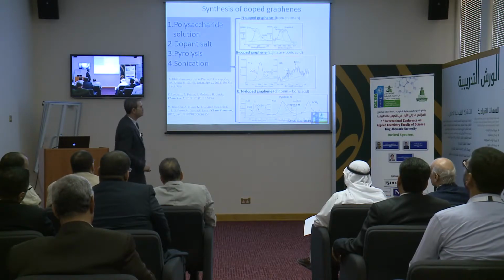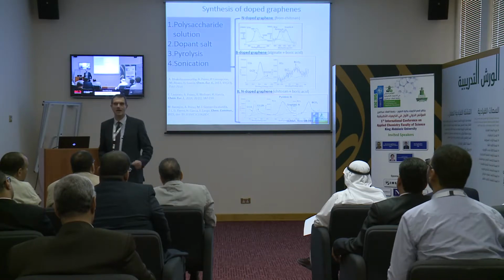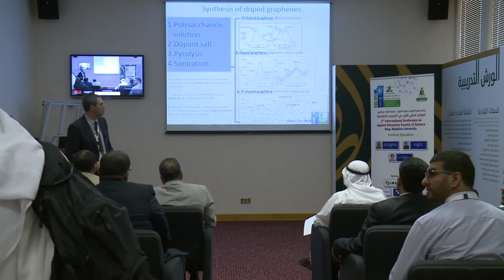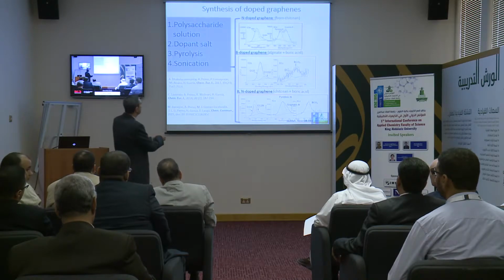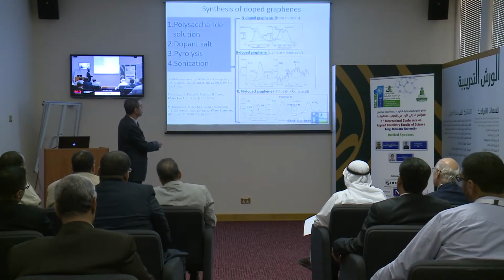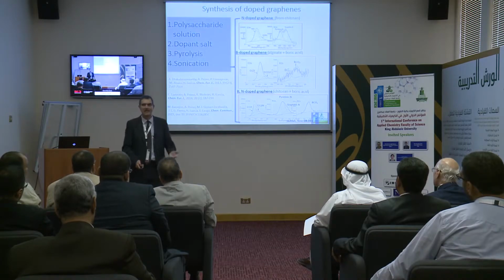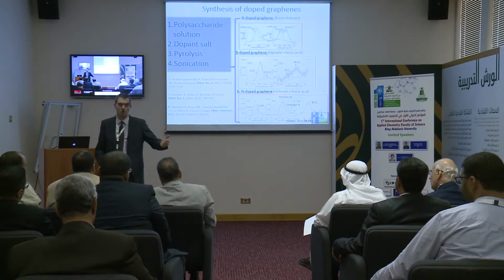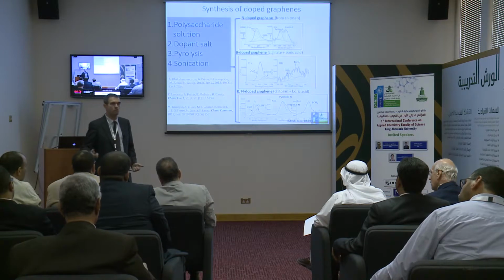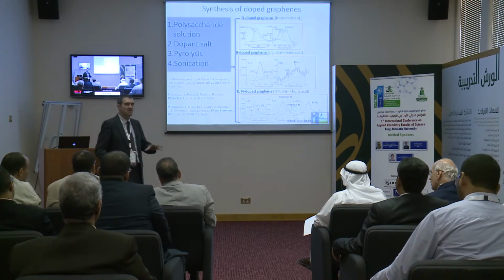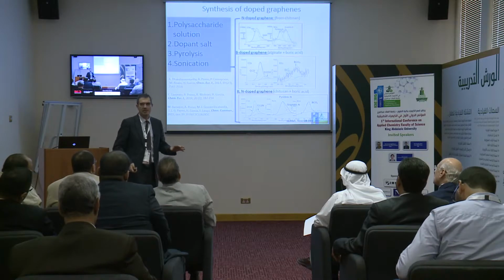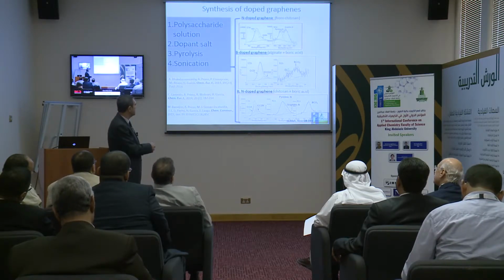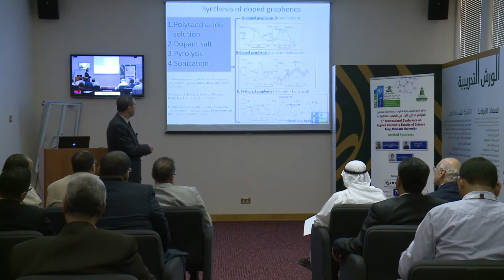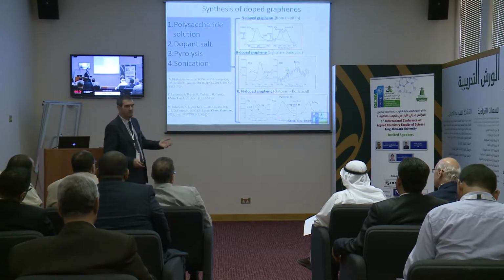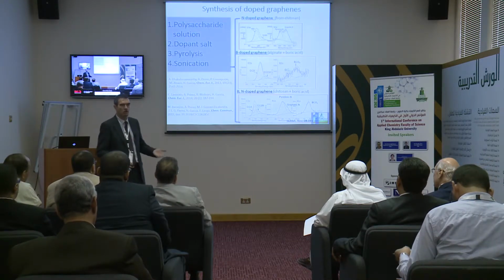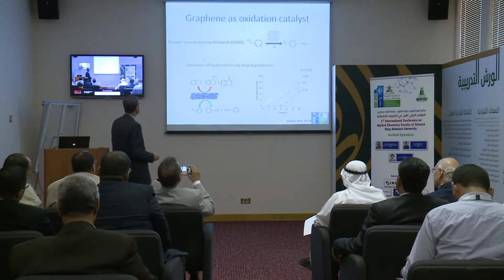Depending on the conditions that you pyrolyze, the amount of boron can be higher or lower, and this depends on the pyrolysis temperature. And also we can prepare graphenes having 2 elements, boron and nitrogen. This is very important from the catalysis point of view, because boron will introduce acidity, nitrogen will introduce basicity. So considering the major reaction mechanisms, acid-base is one of the major ones, and here we have a material that contains both acid and basic sites. And also redox sites, because redox can be quinone, hydroquinone, and these are the effects on graphene.